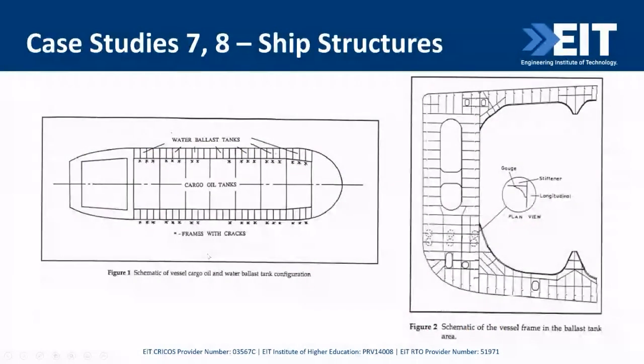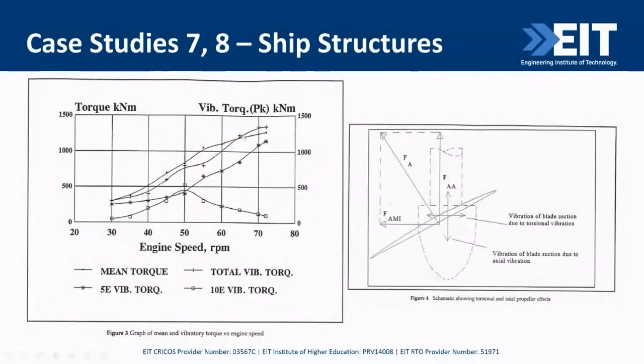It was the 5-cylinder. If you look at the ballast tanks, this is the cracking here, and in the frames above had the cross ties, one cross tie. That's great, but this large panel here wasn't happy, and the 5th order vibratory torque was way too high, up near maximum continuous running. So normally you have a vibratory torque peak, which peaks down here and then reduces, and you'll have a bar speed range down there, and you'll have your operating speed higher up. For some reason, this was put in, and nobody looked at this high vibratory torque at common running speed, and